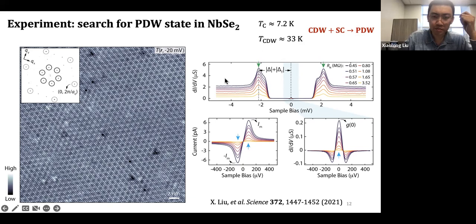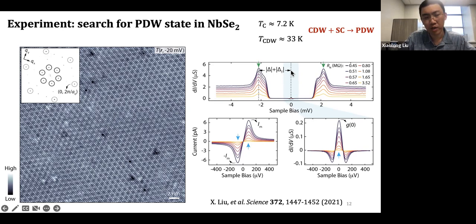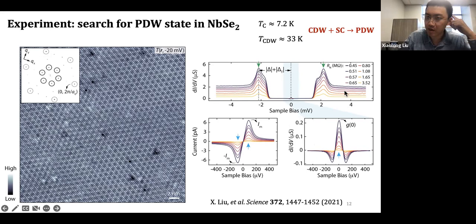Our goal is to search for the signatures of such pair density waves. First we look at the surface using a superconducting niobium tip — the resolution is pretty high, it's atomic. We confirm the superconductivity by looking at the dI/dV spectrum: using a superconducting tip increases the size of the superconductivity gap in your spectrum, as expected. If you zoom into the zero-bias region you can see the characteristic inelastic Josephson tunneling signatures. We know our tip is definitely superconducting. We can measure G₀ directly from lock-in measurements, and it varies as a function of junction resistance R_N as expected.